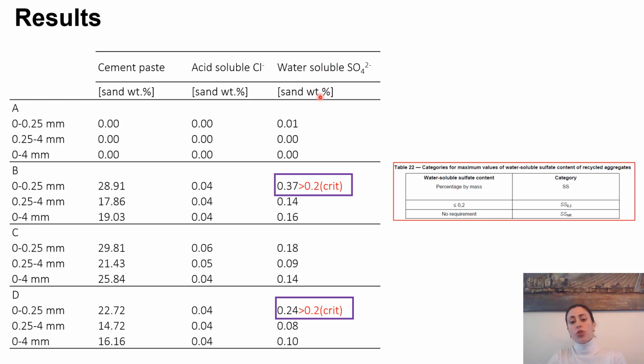Then the water soluble sulfates are actually something different. Here you can see that in the finer fraction, below 250 microns, we have more sulfates than in the coarser fractions, above 250 microns. So what we can see is that it is good to use 0 to 4 millimeters as a total fraction as a replacement to sand, rather than to split it and use the fine fraction as a replacement.